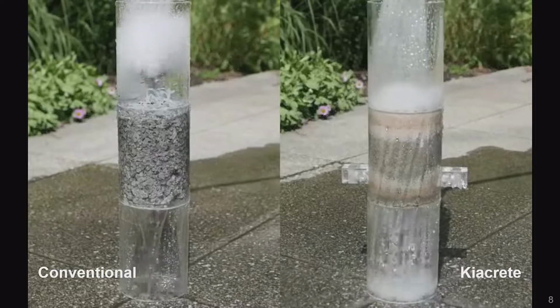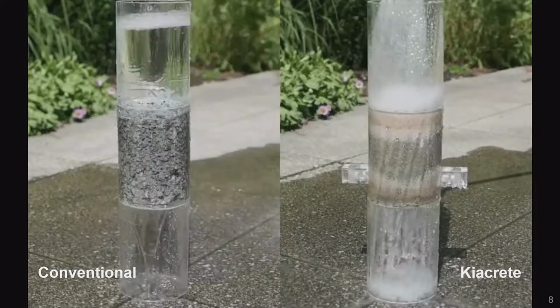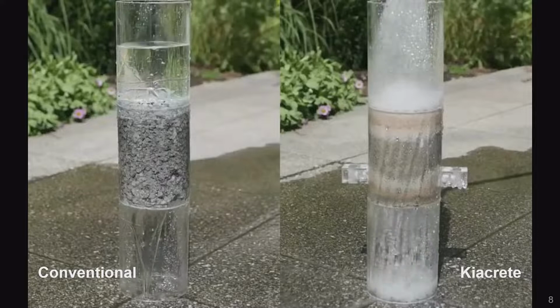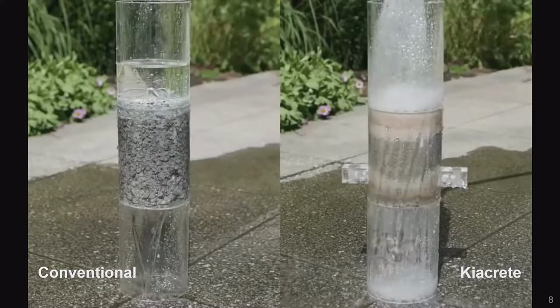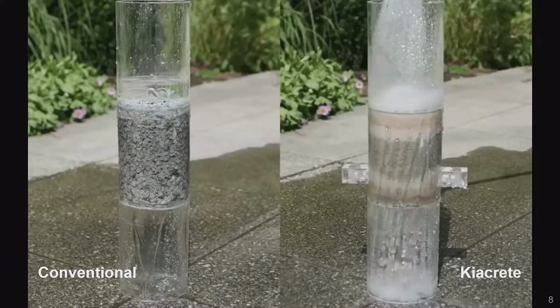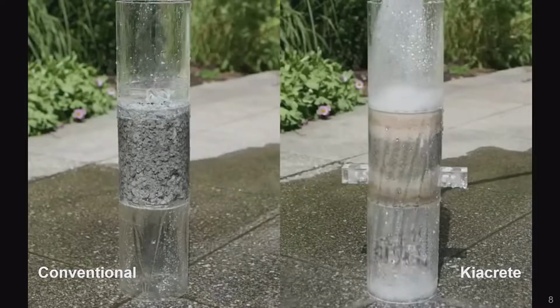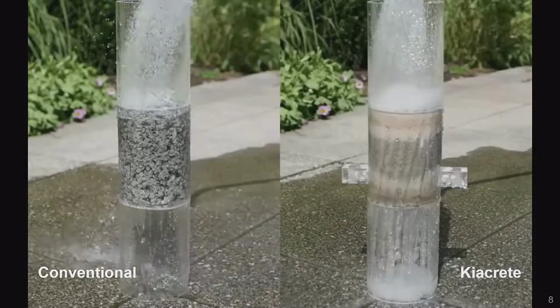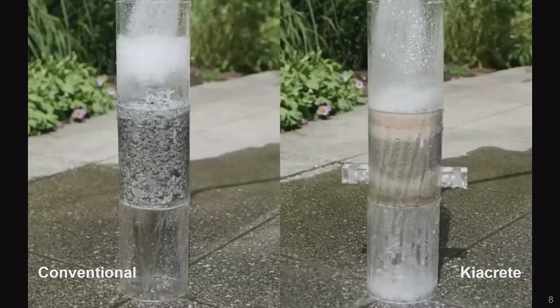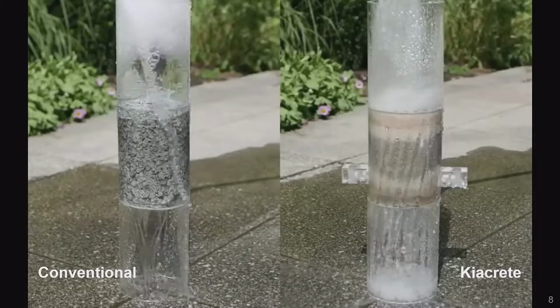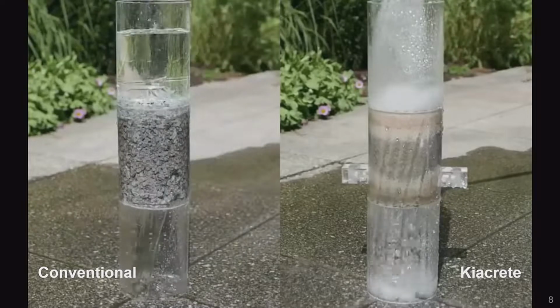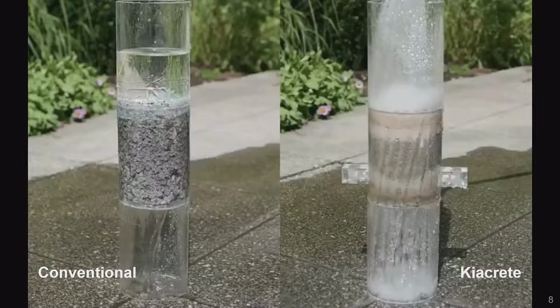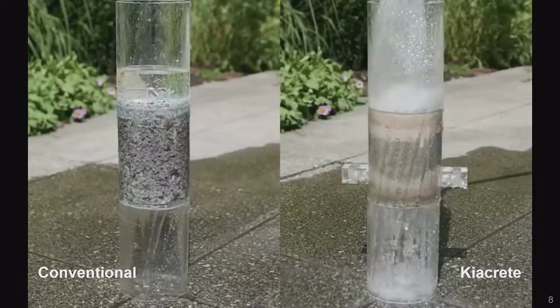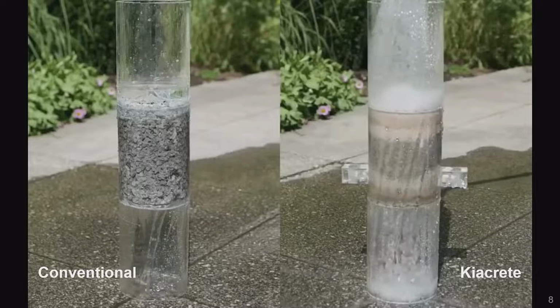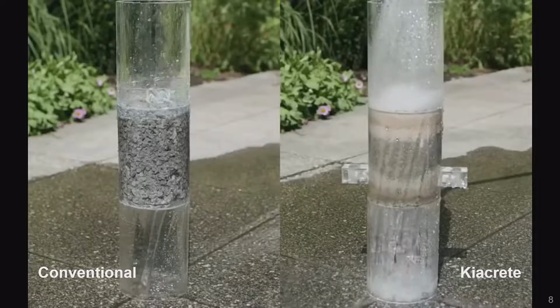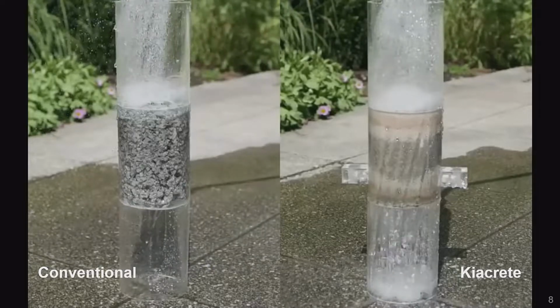So if we quickly have a look at this video, on the left we have the conventional permeable pavement of 20% porosity, and on the right we have Kiacrete of 20% porosity as well. Neither of them are clogged. So as we expose the conventional pavement to the same volume of water as Kiacrete, it quickly becomes overwhelmed by the amount of water that it's receiving, and we need to remove the water source. But in the case of Kiacrete on the right, you can see that it's capable of receiving that volume